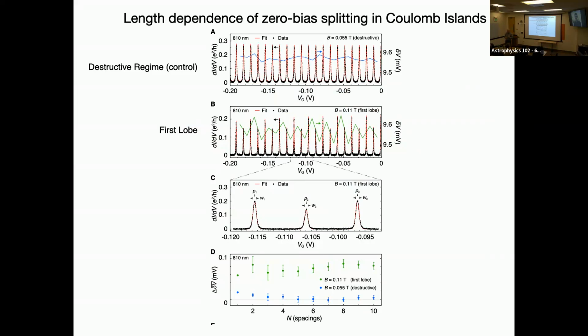Now, what's great about this particular experiment is it comes with its own control experiment. If you go to the destructive regime in the middle, N-I-N-I-N, and if you find even-odd there, you're doing something wrong, because that's a metal island. And you can see that as you increase the number of spacings, this is what happens in the destructive regime at 0.05. And if you go in the first lobe, even the long wire has this non-zero even-odd feature. So it's outside the error bars, it's measurable, although to your eye, those look kind of evenly spaced. But the computer knows.